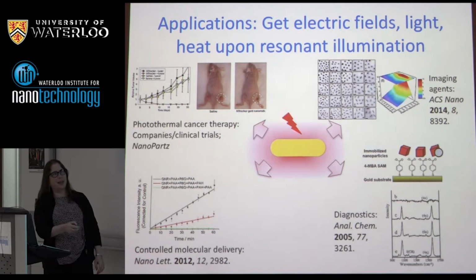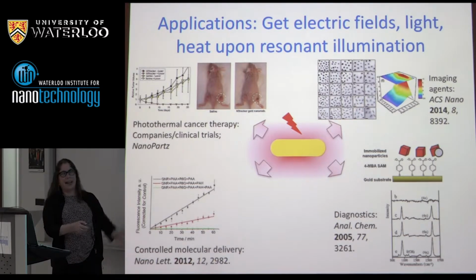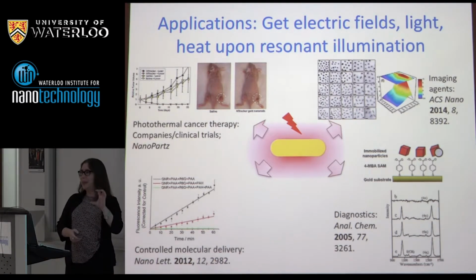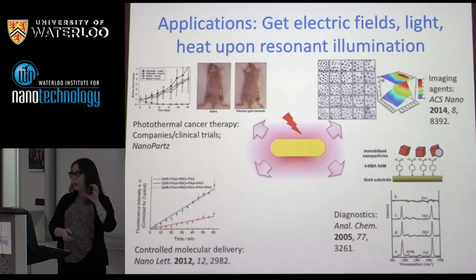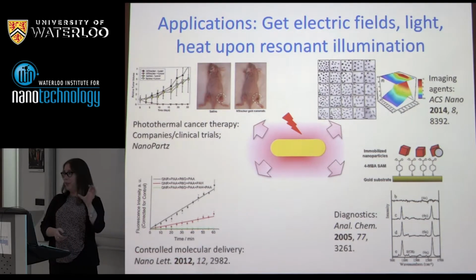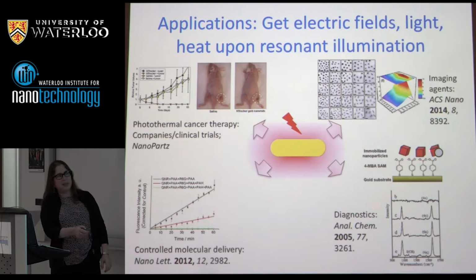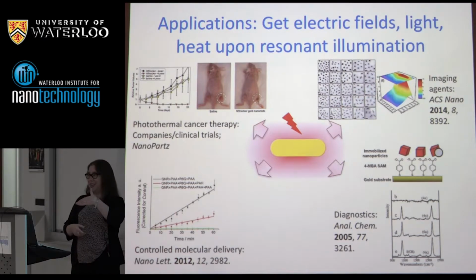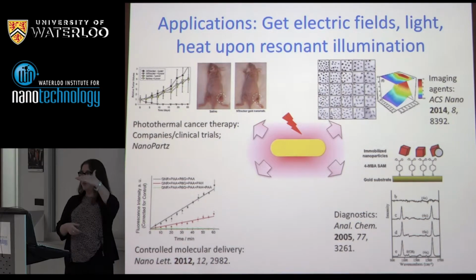So here's my rod. I come in with light that is resonant with one of those 2 plasmon frequencies. And what do I get? I get these electrons moving around, which means I get a big electric field near the surface, which means if you want to do molecular photophysics as a function of electric field, you have the perfect system. So the most famous example of this is surface-enhanced Raman spectroscopy, where a molecule whose Raman modes aren't very visible, when you have a monolayer, suddenly lights up when you sprinkle particles on top because you're coupling the plasmons from this thin metal film to these particles here. I'll show you this later. Some photophysical properties of molecules, if you're too close to a metal surface, it's not going to be good, so you want to be a certain distance away before you start seeing something.